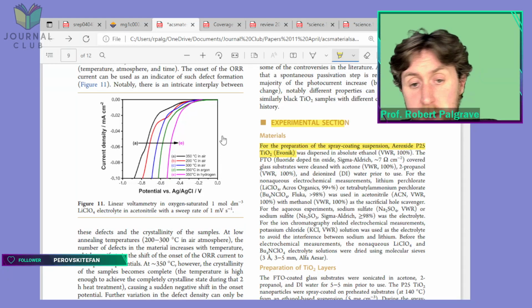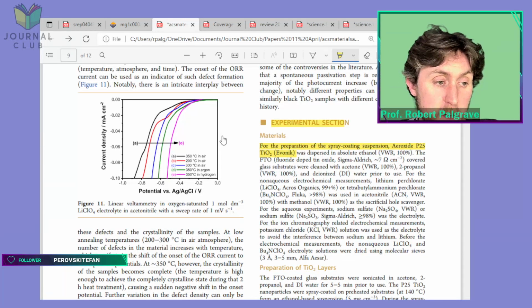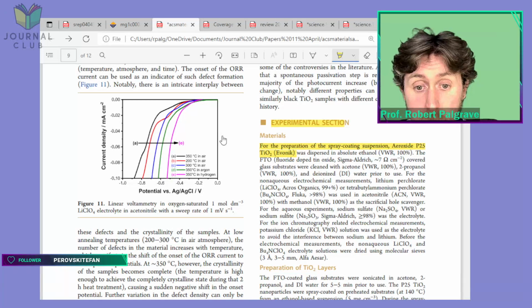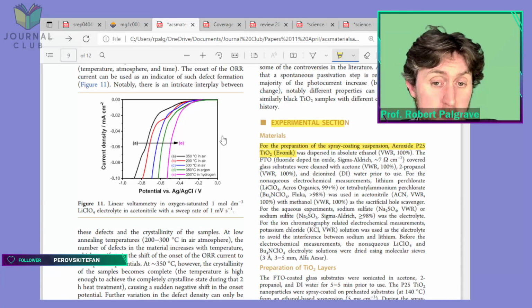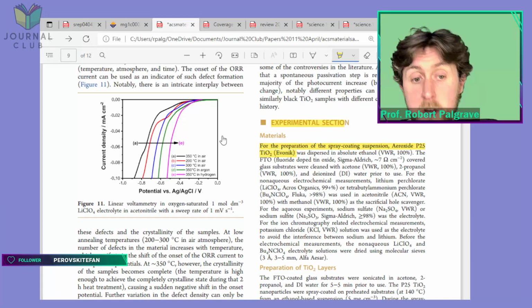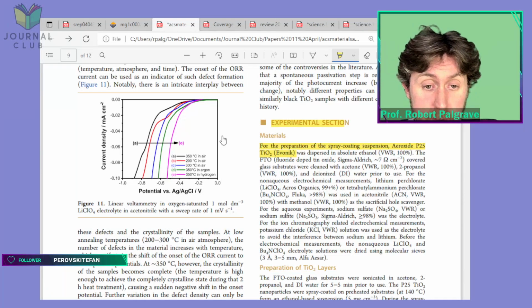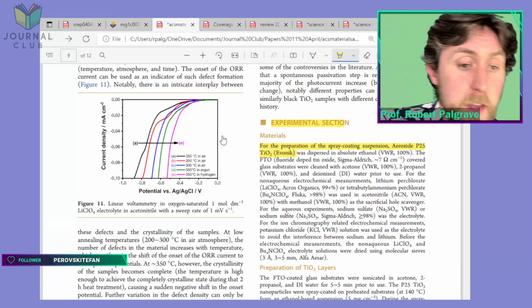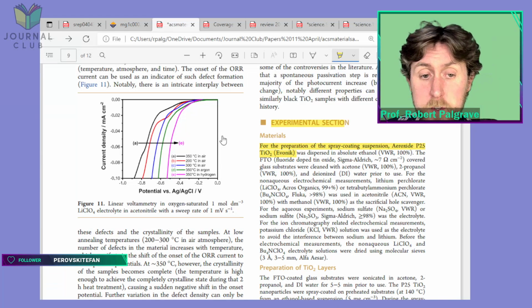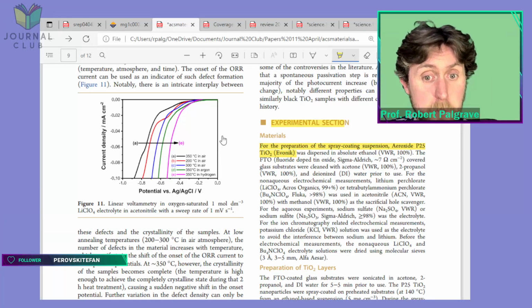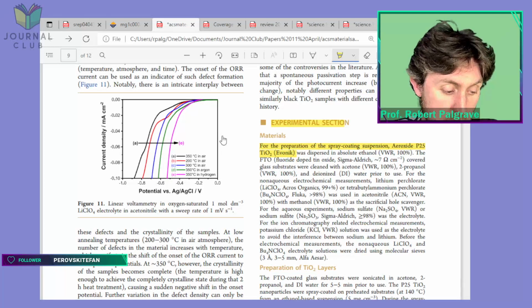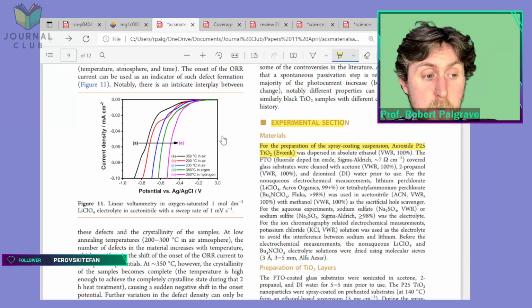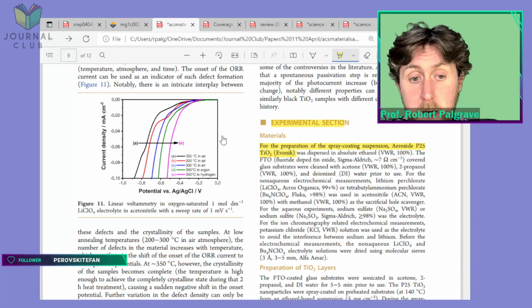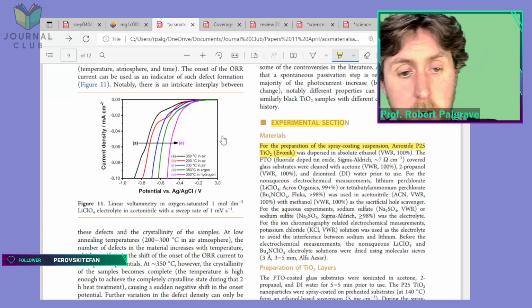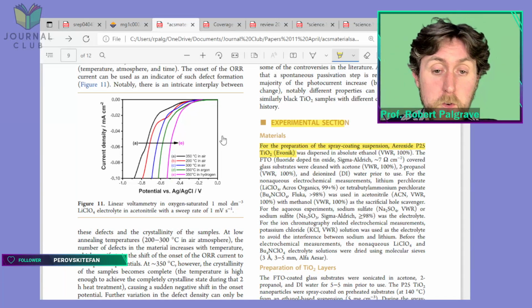So kind of the gold standard of catalyst comparisons, especially for TiO2. P25 is a nanomaterial, so it's nanoparticles of TiO2. I think the 25 is to do with the size, if I remember right. So I think it's about 25 nanometer particles. So pretty small particles of TiO2, very high surface area. So that gives you high absolute catalytic activity, which is one of the attractive parts of that material. Also, the fact it's mixed phase, anatase and rutile, is pretty important as well. I think there's a lot of papers about the synergistic relationship between anatase and rutile for photocatalysis. So the idea that you have both of these phases there at the same time is thought to be very important for P25's activity.